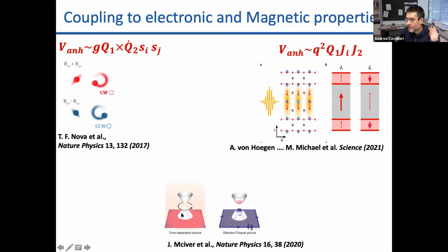Other work that we've done has been, for example, in graphene, where by driving graphene close to a phonon resonance circularly, what my postdoc James McIver showed is that you can open a topological gap in a material which otherwise does not have any gap, thereby showing a light-induced anomalous Hall effect in a system that does not otherwise have topologically interesting structure. And he has shown that in this way you can mimic the Haldane Hamiltonian in a very elegant way. And thirdly, this is newer work where we look at the coupling between phonons and plasmons. These are only examples of things that can be done, and should lead me into a few slides on what I really wanted to tell you, which is the things that I'm most interested in in our current work.